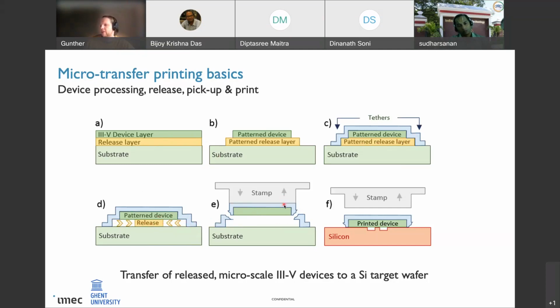So now you can come in with your stamp, and with that stamp you laminate the device and pick it up, thereby breaking the tether. And similarly on the target wafer, you then print the device on the silicon target wafer. Now again, this picture shows a single device that's being picked up and printed, but this is a process that can be done massively parallel.